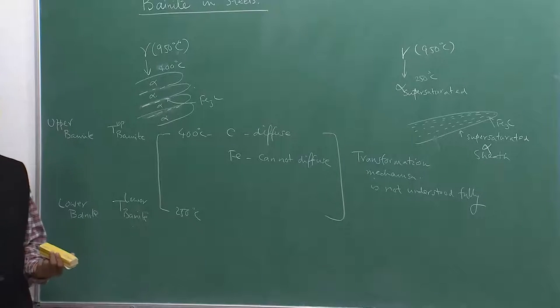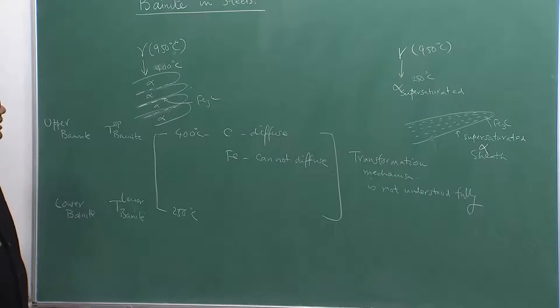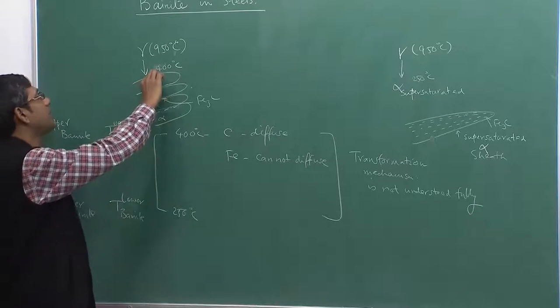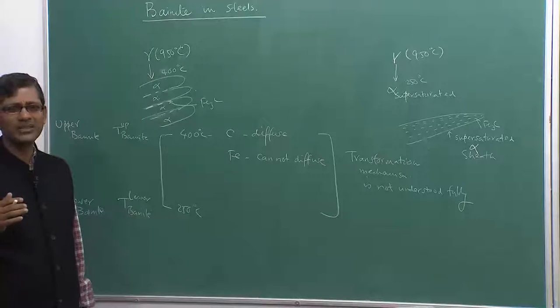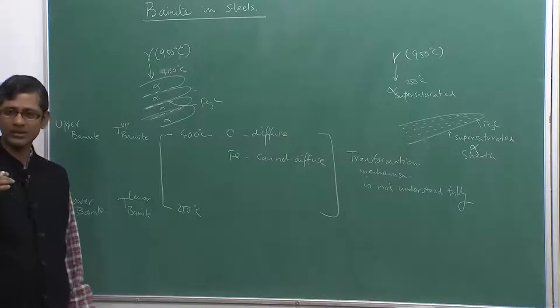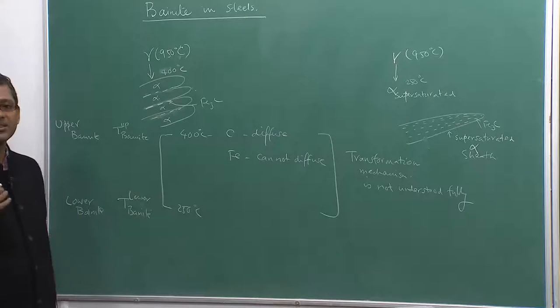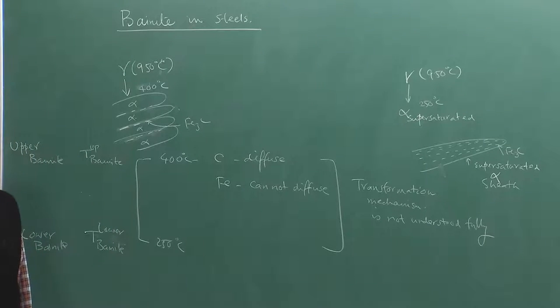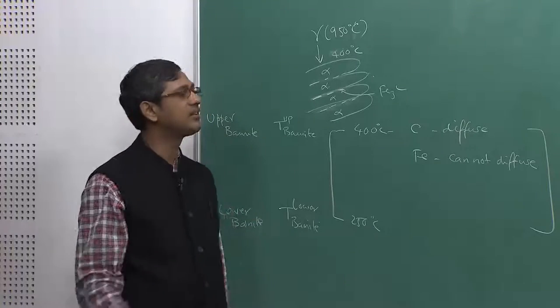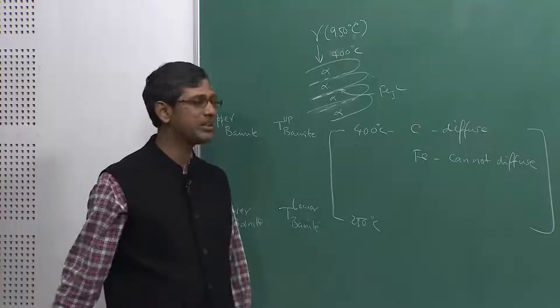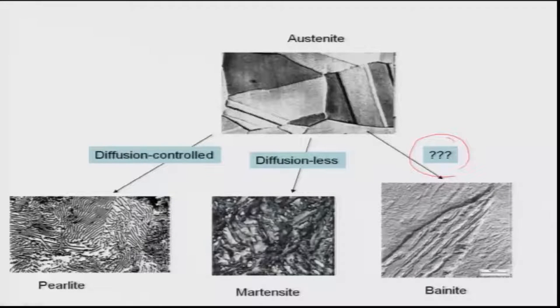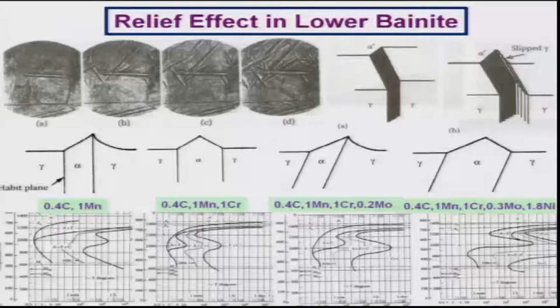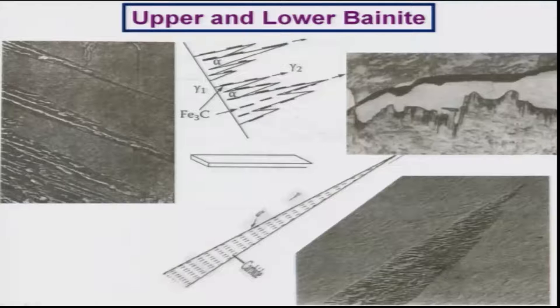By adjusting the alloy chemistry and processing conditions, these plates can be made nanometer-thick instead of micrometer-thick. Professor Harry Bhadeshia from Cambridge has researched this extensively, and bainite is now an industrial product. It is produced by POSCO steel plants in Korea, with much higher strength than classical pearlite — even very fine-scale pearlite cannot match the strength of bainite. Depending on your application, one can change these morphologies.